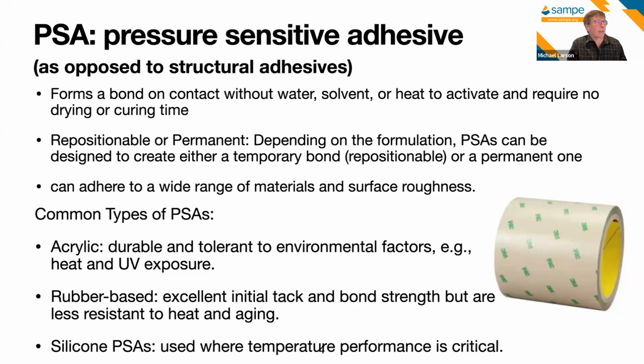So how do we define them then? These form a bond on contact without needing water, solvent, or heat to activate. So this is not a two-part thing like an epoxy. They can be repositionable or permanent, depending on their formulation. And they can adhere to a wide range of materials and surface roughness, typically as long as we can get complete wetting of the surface in order to take advantage of the PSA's capability.